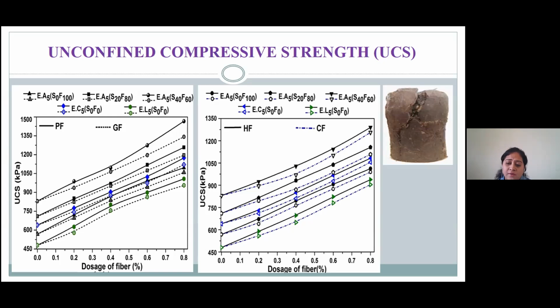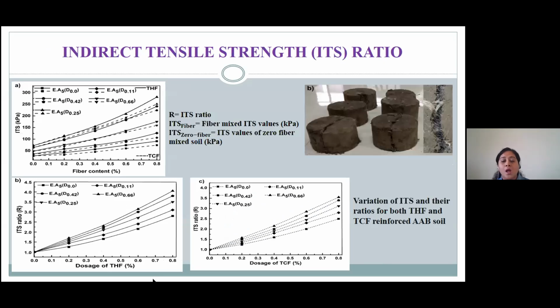The substantial variations in shear strength depend upon fiber roughness, confinement bonding, contact area, and interfacial friction. However, we found that generally an inclusion of 0.8% fiber leads to the highest strength as well as enhances the workability. If we go beyond that, the workability is drastically reduced.